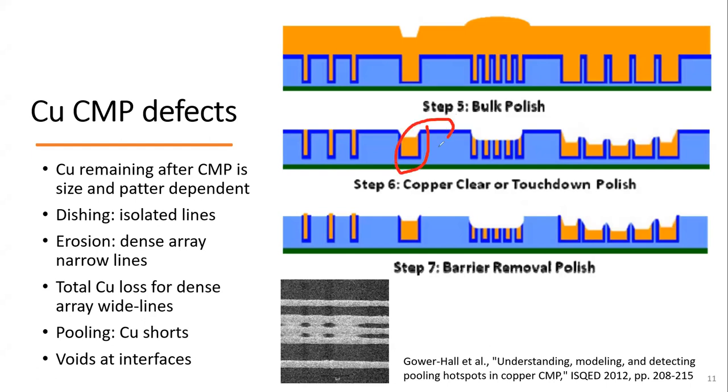Dishing means that with a single big fat line here, you try to polish everything nicely like this, right? Everything nicely means that the copper and its neighbor are on the same line, same level. But because copper is softer, when you CMP any wafer, you will find the soft material is kind of easy to remove more. That's the reason it dished out, becoming a dishing. It's called a small dish here. The shape's like a dish. But if you have a very narrow line array put together and everybody is removed, this is a big dish. The big dish is called erosion, right? Small dish is called dishing, and the big dish that covers the whole area of a dense array,